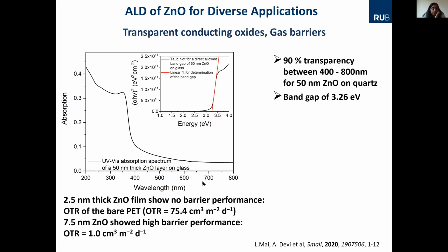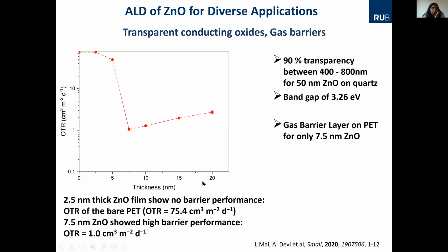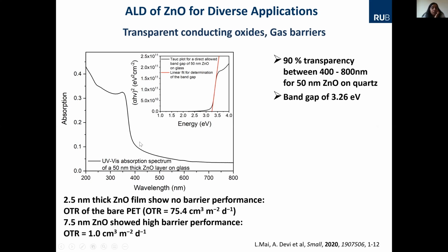Yeah, it had a very high transparency. In the case of the optical band gap, it was around 3.26 that we estimated, which is sort of agreeing with the literature known values.